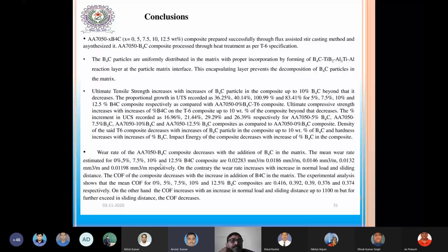If we talk about their observations, the wear rate of these aluminum 7050 B4C composites decreases with the addition of B4C in the matrix, and the mean wear rate is given for the 5%, 7.5%, 10%, and 12.5% composites. So these are their observations and results. We can go through that.